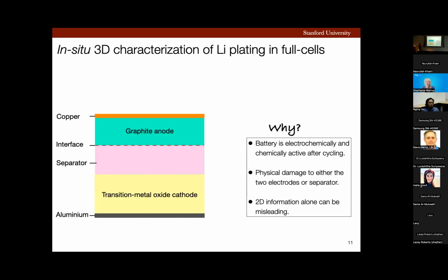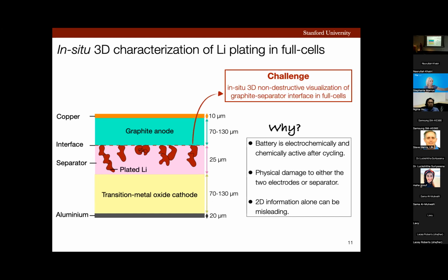Here, I'm showing a schematic of a lithium-ion battery that consists of copper and aluminum current collectors, graphite anode, transition metal or NMC cathode, separator, and this graphite-separator interface. Now, lithium plating is hypothesized to start plating at this interface and then form these structures that grow through the separator. Now, it is extremely challenging to understand the morphological behavior and spatial heterogeneities of lithium plating in 3 dimensions in situ in a full cell battery, because visualizing this interface non-destructively in a full cell battery in 3D is a challenge in itself, especially at these micron relevant length scales.